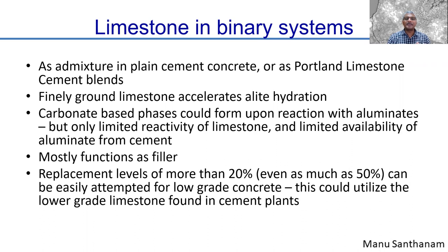So the soluble carbonate can actually go ahead and react with the aluminates that are available in the cementitious material and then lead to the formation of products like carboaluminates. Again, these are solid products that are going to be occupying the volume. I'll talk about that a little bit later. But that is limited because, first of all, the aluminates are already busy reacting with the sulfates in cementitious systems. And there's only so much of carbonate that can actually dissolve.